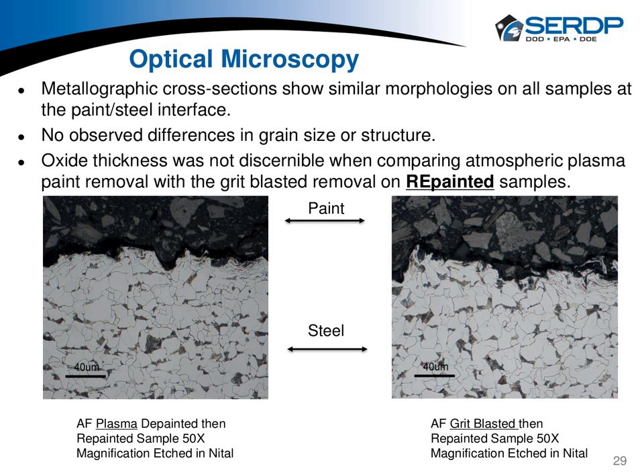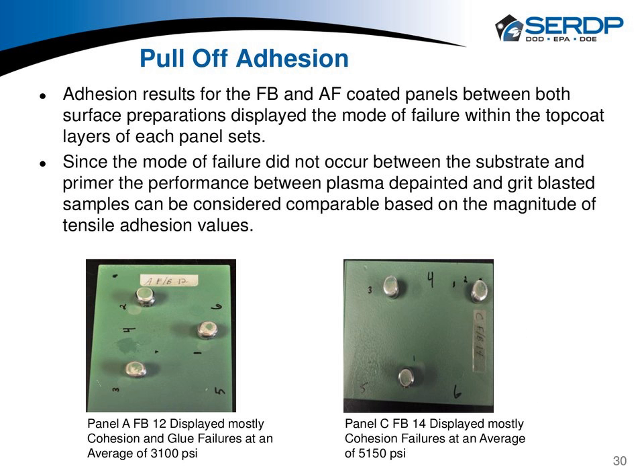So let's move on to some of the performance tests, and these are common if you're familiar with these. The first one, and notice primer only, the weak link in the system, is typical of a pull-off adhesion test, whether this is done wet or dry, to determine if there's a good bond of the primer to the surface. That's the most important thing, otherwise the whole system's going to fall off. The numbers ranged anywhere from about 3,000 to 5,000 psi. We did see some variation, but it was pretty normal scatter for the statistics. On all of the samples that we had, the mode of failure was within the top coat, and that told us that we had really good adhesion dry before any kind of testing whatsoever.